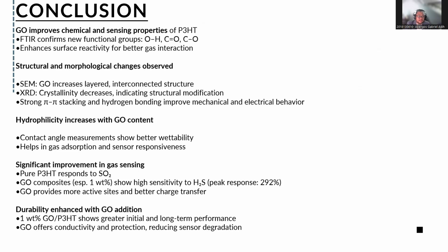responsive to SO2. For the conclusion, GO improves the chemical and sensing properties of P3HT, which is confirmed by FTIR, as stated in the new functional groups, enhancing surface reactivity for better gas interaction. Structural and morphological changes are observed in SEM as GO increases the layered and interconnected structure (XRD). Crystallinity decreases but indicates structural modification, which is the strong pi-to-pi stacking and hydrogen bonding, improving the mechanical and electrical behavior. So hydrophilicity increases with GO content. Contact angle measurements show better wettability, which helps gas adsorption and response in sensors.